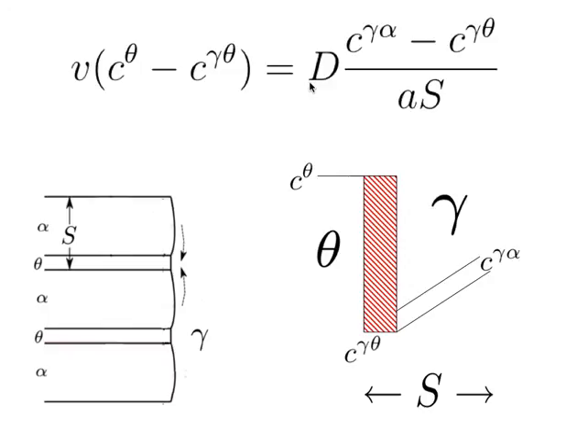There is a difficulty: we do not have a value for the interlamellar spacing, and if the spacing goes to zero, the velocity goes to infinity — the same sort of problem we had with Widmanstätten ferrite. We have a function giving velocity as a function of interlamellar spacing, but no explicit velocity. We need a theory for the interlamellar spacing.